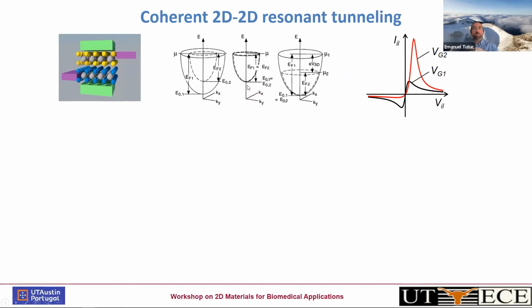But on the other hand, if somehow we mismatch these band structures in energy space, either by applying a bias of some type, a gate bias or an interlayer bias, if we conserve energy, we don't conserve momentum, and vice versa. And this is illustrated here. If we were to take one electron from here and move it to the opposite layer, we may conserve energy, but don't conserve momentum. So if we enforce momentum and energy conservation, we can have either high or low interlayer tunneling, depending on these two conditions.